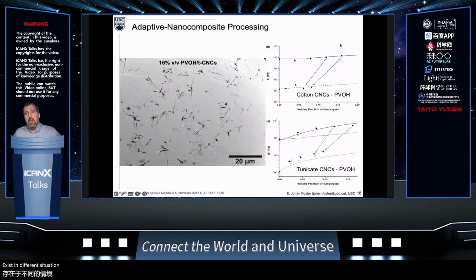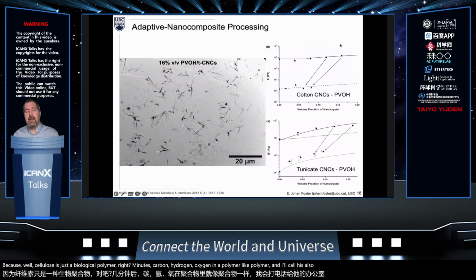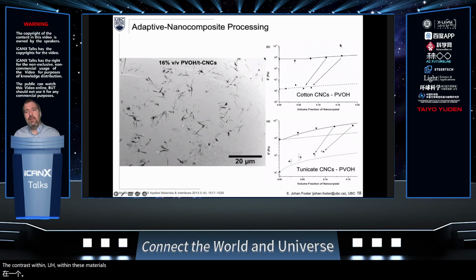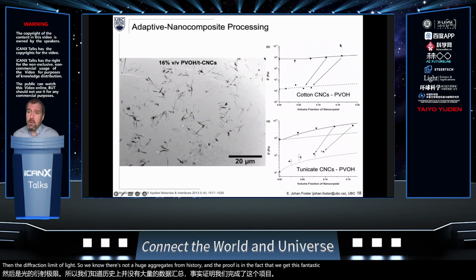Okay. You might ask, well, are the cellulose nanocrystals actually dispersed? It looks like they are, yes. It's very difficult to image the cellulose nanocrystals within a polymer matrix because, well, cellulose is just a biological polymer, right? I mean, it's carbon, hydrogen, and oxygen, and a polymer like polyvinyl alcohol is also just carbon, hydrogen, and oxygen. So you don't get very good contrast within these materials. And so images like this, where we show mostly dispersed cellulose nanocrystals within this material, seem to indicate that they're very well dispersed. We can see objects that are larger than the diffraction limit of light, so we know there's not huge aggregates within this material. And the proof is in the fact that we get this fantastic reinforcement of the polymer.